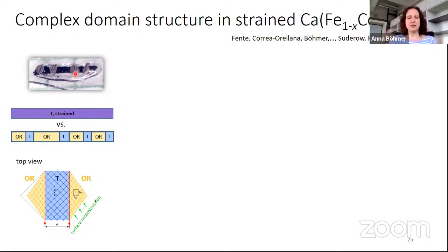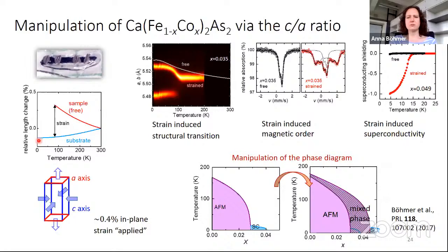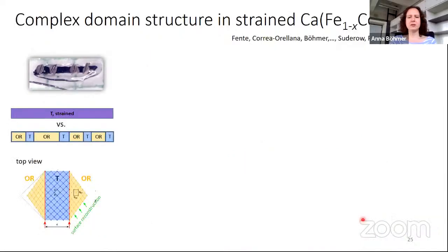But it's strained, it doesn't have the length it wants. And it turns out, instead of staying that way, it only goes partially through that phase transition. We have some regions that are not strained and, without going through the phase transition, and other regions that have gone through that phase transition. By that phase transition, I really mean the structural one here. So we have part of our sample that's here, and a part of our sample that's here, all over the phase diagram, well, all over the mixed phase.